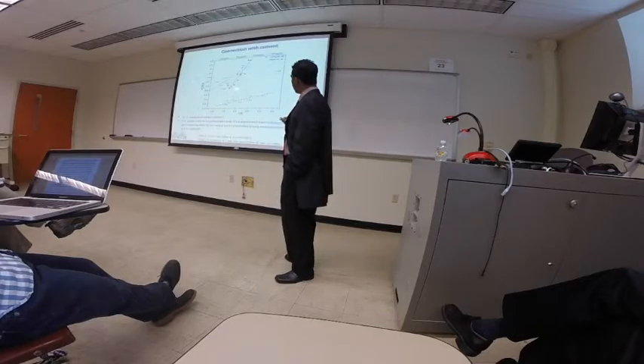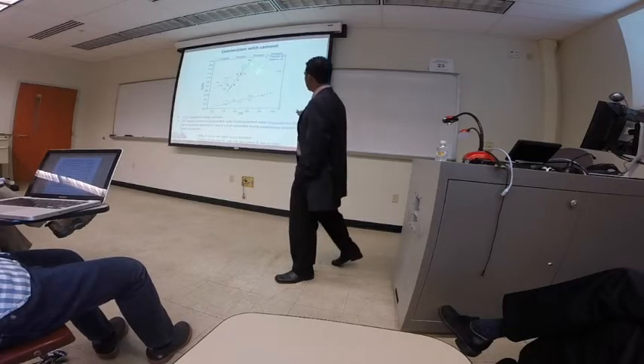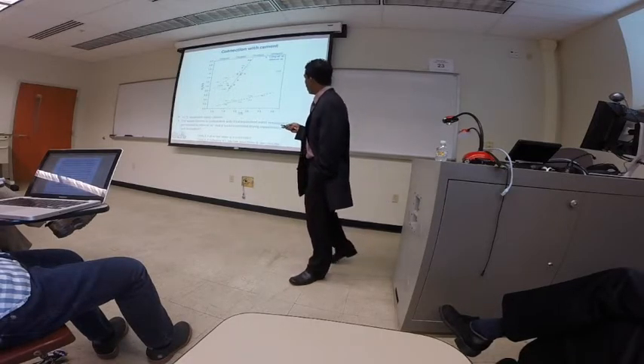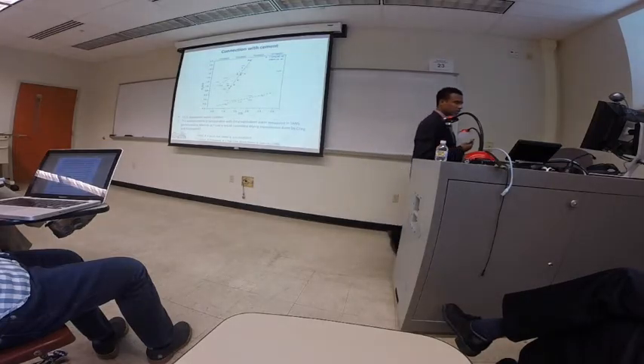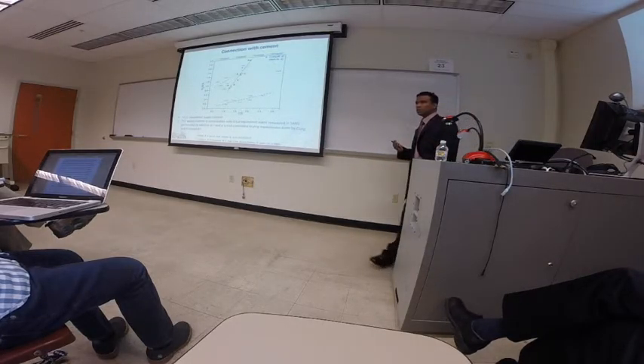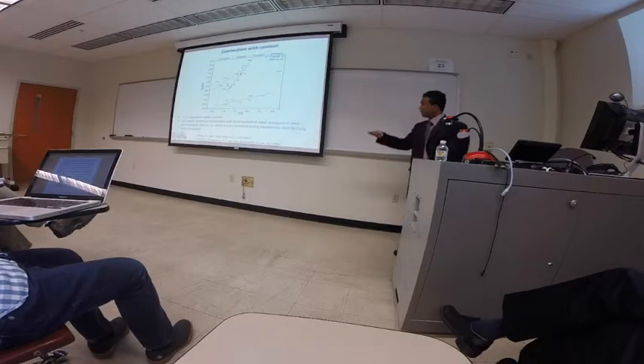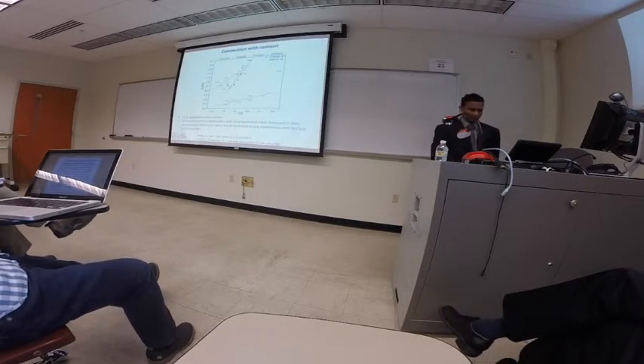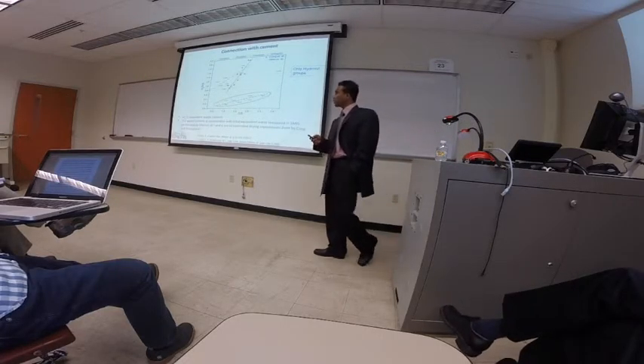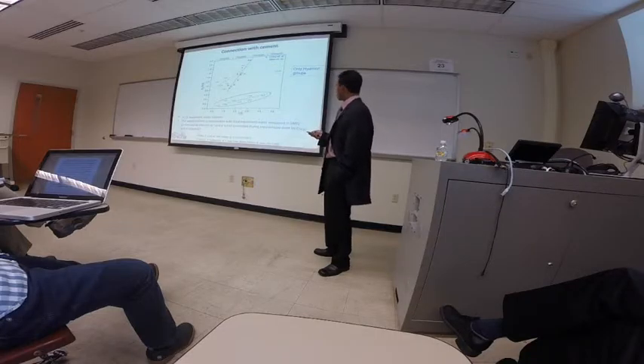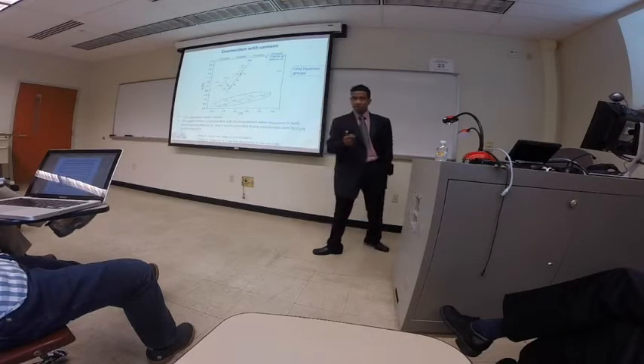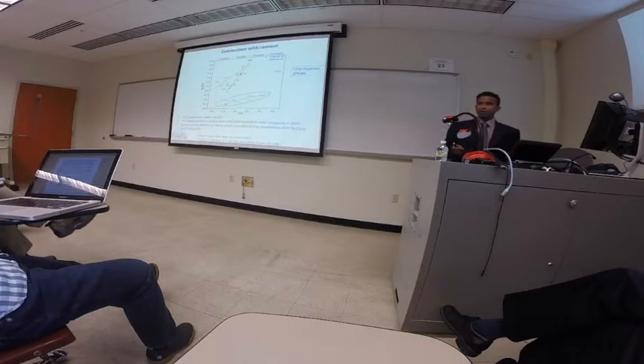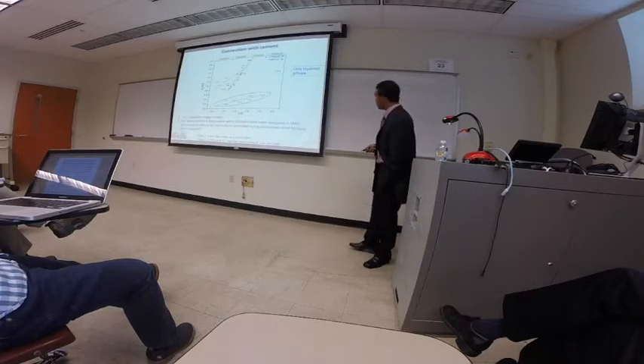And indeed, some of our crystals, especially the D group crystals, have a close relation with the experimental findings, which gives you the promise that maybe these crystals will tell something about real cement at the end of the day. But you can see there's a separate trend here, so we looked at those crystals closely, and we found that these crystals have only hydroxyl groups in the interlayer or within the crystal structure, and no water, which makes sense, as real cement one can assume to have both structural water and hydroxyl together.